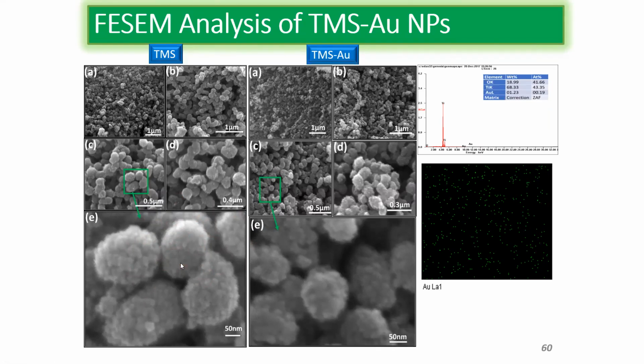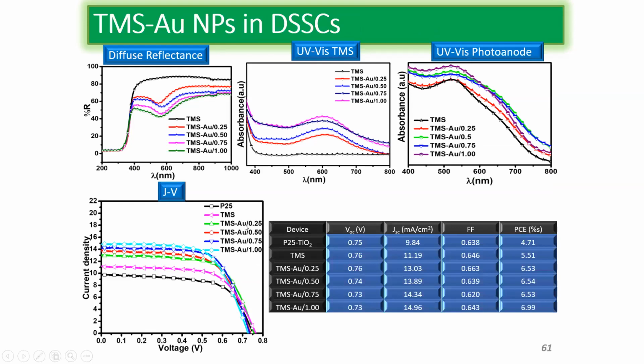I explained that earlier. And similarly, this is just TiO2, and when I increase the gold doping, we see that because of the SPR effect we get an absorption peak. This is a reflection, so in absorption we'll get a peak. And we also see that when we increase the loading, some red shift is happening. It took almost 1 month for me to understand why this red shift is happening. I overall found that maybe with increasing percentage, some aggregation of gold is happening, and because of this, some red shift is happening.